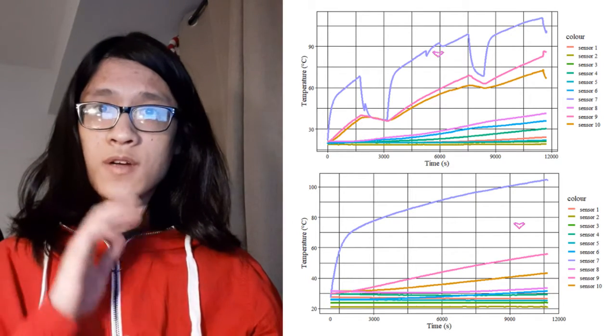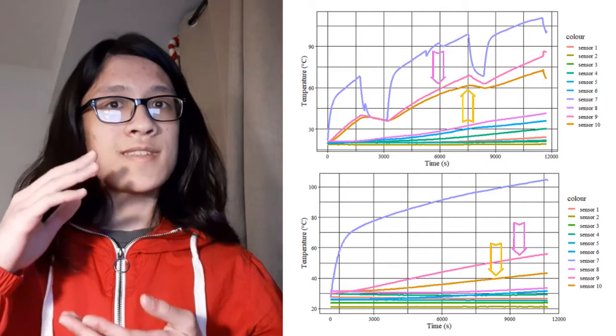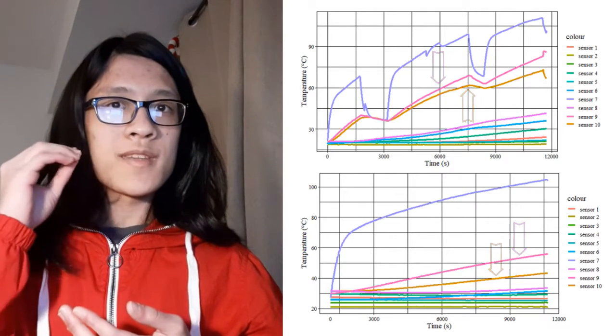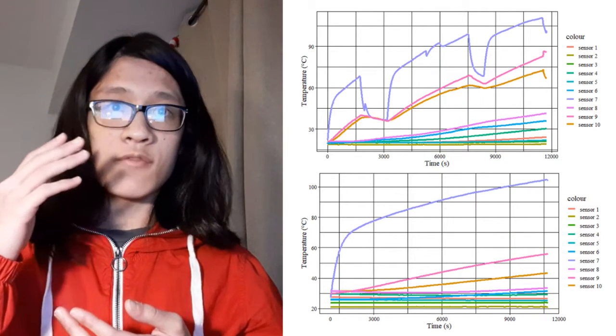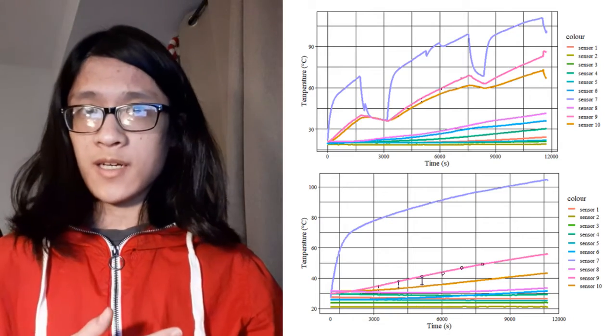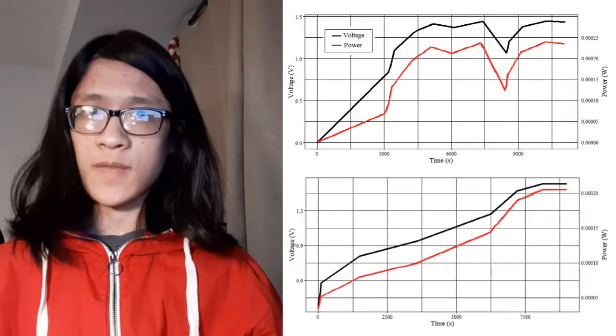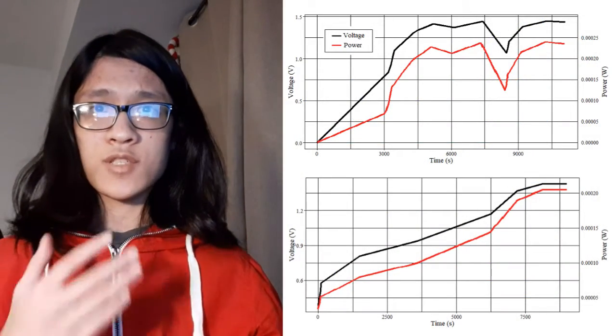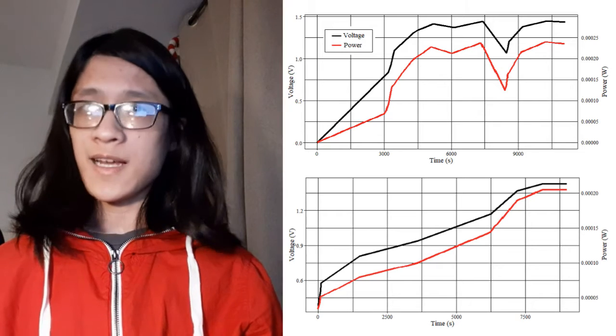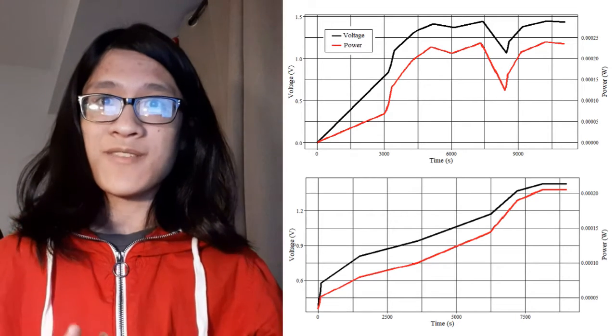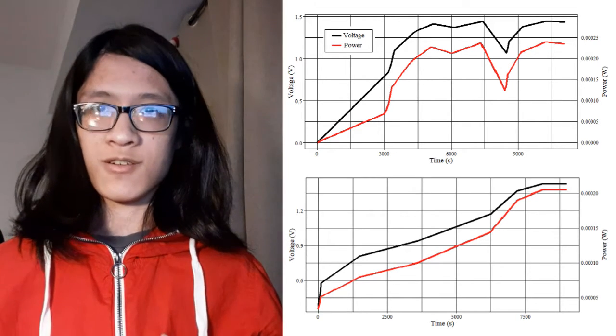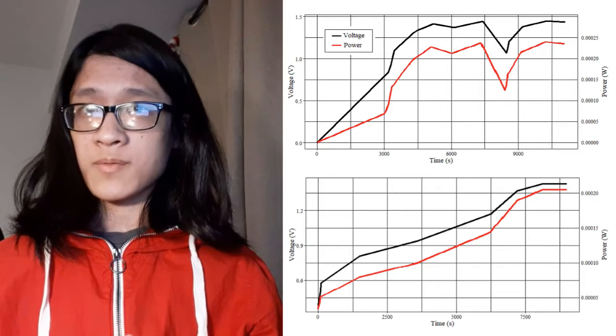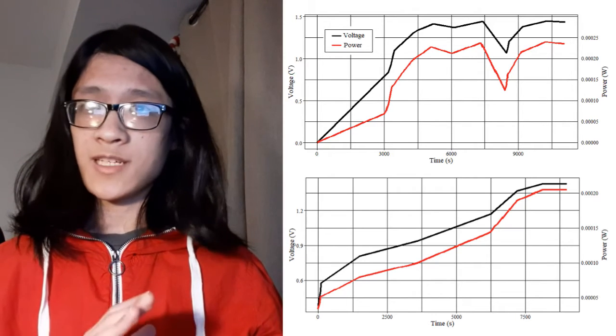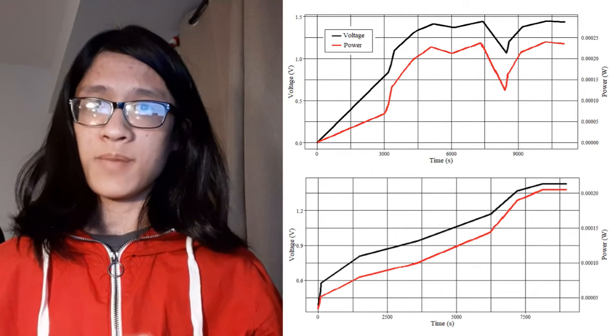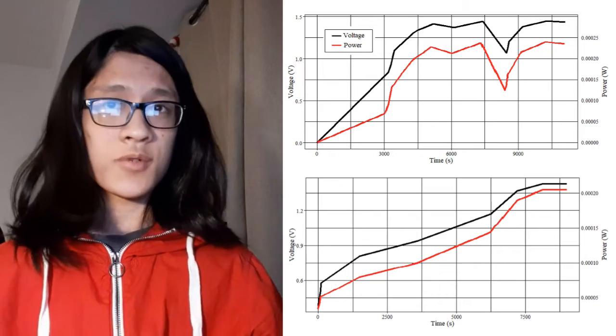We found that both the hot and cold side of the TEG increased in temperature throughout the experiment, but notably that the hot side increased with a much higher rate of growth than the cold side, demonstrating an increasing temperature differential over time. Also recording the voltage generated by the heat transfer across the TEG, as expected, we found an increasing graph that mirrored the changes in temperature differential. We also found, by comparing the two experiments and referring to our simulations, that overall an increase in input heat power correlated with an increase in open circuit voltage from the TEGs.